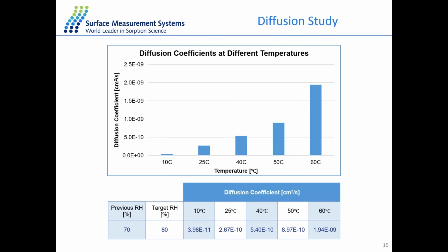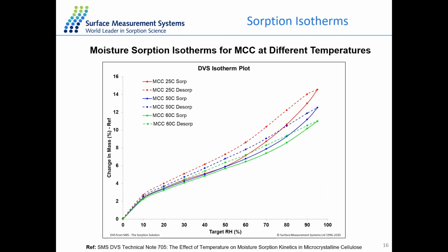So in the case of the microcrystalline cellulose, the diffusion coefficient is calculated with the average particle size of 50 micrometers and at the stage from 70 to 80% RH. These diffusion constants also show a trend of increasing with increasing temperature, which means temperature will help with the faster diffusion of the water molecule into the microcrystalline cellulose powder. So that's just some data about the diffusion constant at different temperatures.